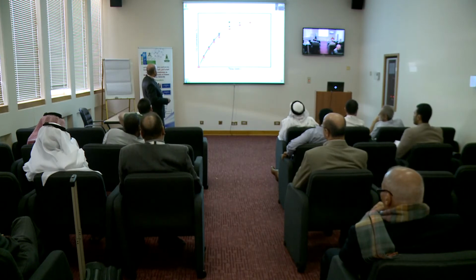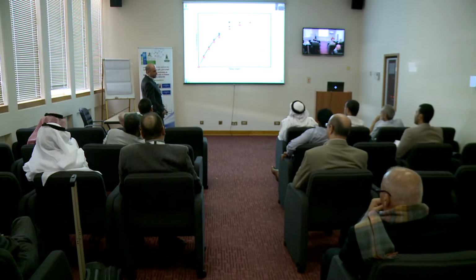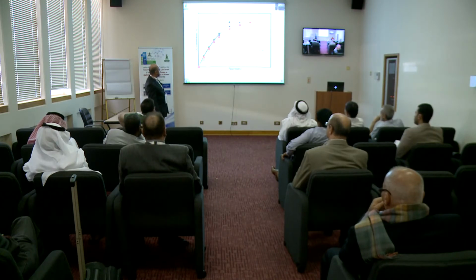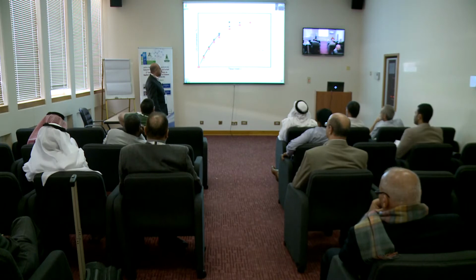And again, we oxidize the carbon monoxide to carbon dioxide. Carbon dioxide is more friendly, and can be converted to many other things, but carbon monoxide is a toxic gas. When we increase the amount of the catalyst itself, the manganese oxide, we can get more conversion of the carbon monoxide to carbon dioxide. This is for air protection.